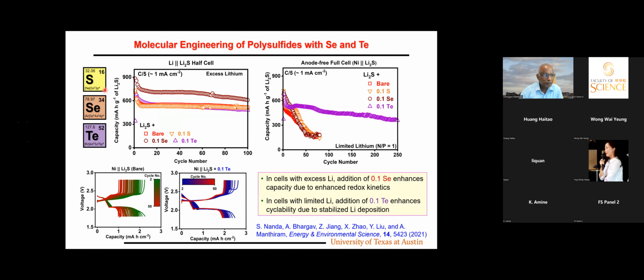First, if you look at sulfur, selenium, and tellurium, they're all in the same group in the periodic table. So here we take Li2S, and we are doing, as you see here, an anode-free cell. That means we take Li2S on the cathode side. At the anode side, we can make a cell with lithium metal, one option. The other configuration is we have Li2S with a nickel current collector on the cathode, and at the anode there is no free lithium at all, so it is called an anode-free full cell.